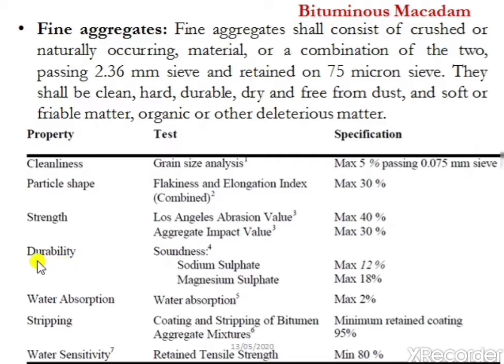The next test is durability. The durability of the aggregates is tested by using sodium sulfate and magnesium sulfate. When the aggregates are tested for durability using sodium sulfate, the value should be within 12%, or a maximum of 12%. When the aggregates are tested with magnesium sulfate, the result should be within 18%, or a maximum of 18%.